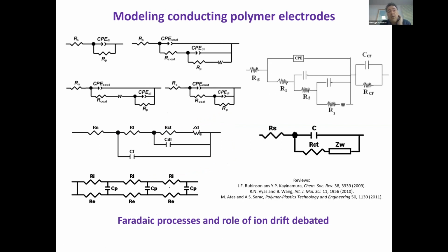Now, going a bit more over the literature, if you look into the modeling that has been done for the electrochemical characteristics of these systems by using equivalent circuits, you will notice again there's no consensus. There are all kinds of different circuits that are being used, often with nonlinear elements, such as this constant phase element or this Warburg element here, that seem to imply Faradaic processes. There is also, if you delve a little bit more into the language, the motion of ions in these films is often termed diffusion. And whether there is drift, whether there is a field inside these polymers that ions can respond to, is something that is debated. So there is scope for taking a new look at this old problem.